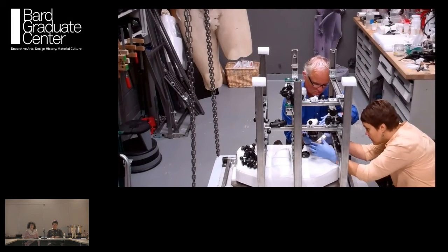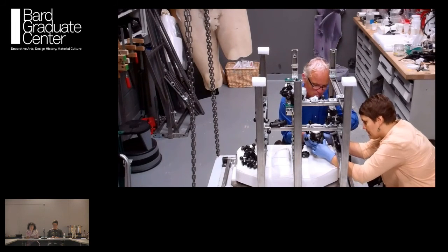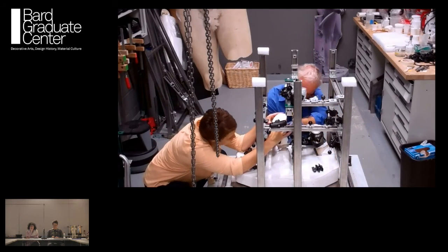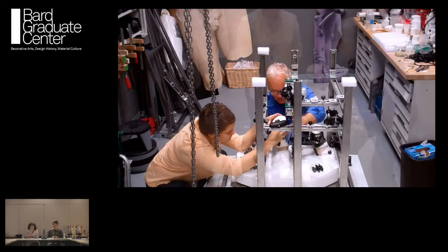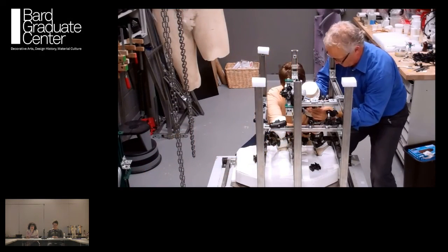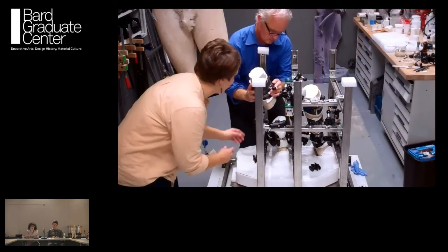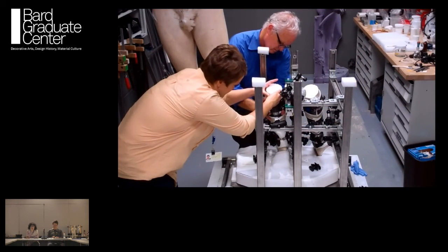The dry stacking method involved adhering one joint at a time, each time stacking all of the leg fragments, and then raising them with the lift table to meet the torso. This technique allowed us to use the weight of the sculpture to clamp and hold the joints while the acrylic adhesive reached full strength. It was a system of self-clamping, if you will, applying the same amount of pressure that would be exerted on each of the joints when the sculpture would once again stand freely.